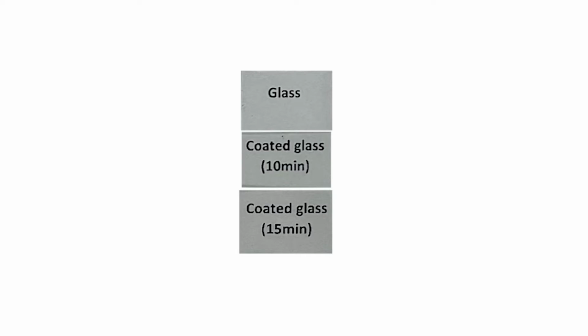So what we did here at IIT Gandhinagar, we have basically created a surface coating which consists of an amorphous non-stoichiometric version of titanium dioxide. So this is how it looks. You can see this is glass, and you can have this surface coating on any kind of surface at room temperature. So this is a coated glass.